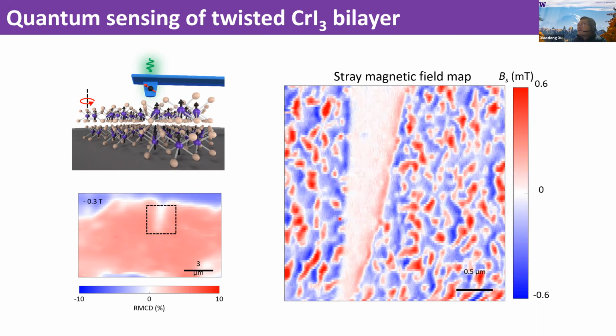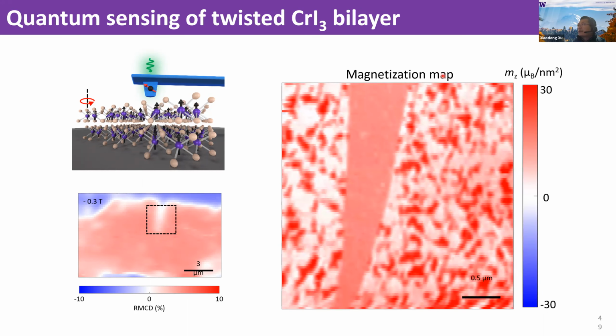And what I show you here is a stray magnetic field mapping using this single spin quantum magnetometry. This map looks very different from my optical measurements. Again, the map I show you here is the stray magnetic field. The next one I show you is a reconstructed magnetization map. Okay, so there are a few interesting features. First, you see this little white feature here in the optical MCD imaging. This little white area is actually a crack during the transfer. So basically, there's a monolayer, and there's a crack in the twisted bilayer. So it's this monolayer. That's why we see this homogeneous magnetization at 15 μB.